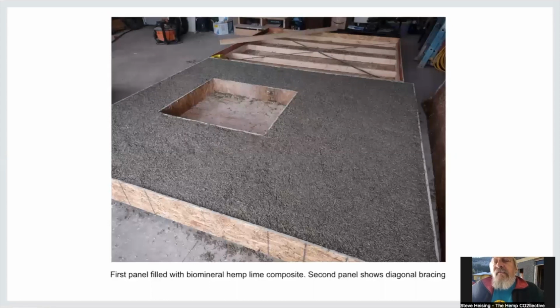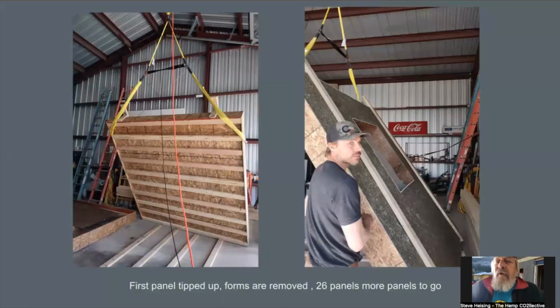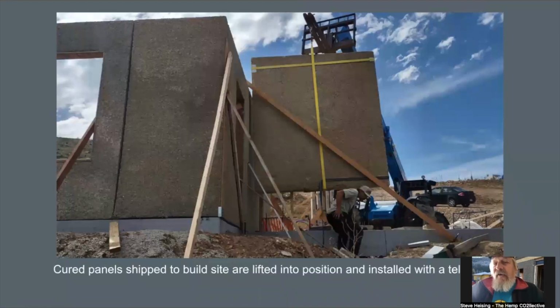There's the form filled with hempcrete. And we're tipping up the first one, and heck, it's working. So far, so good. Only 26 more to go. And here we're actually, after having trucked them across the state, and Glenwood Canyon was closed, so they actually had to go through Wyoming to get here. And I would never recommend doing that, but of the 27 panels, only 3 of them had any damage.